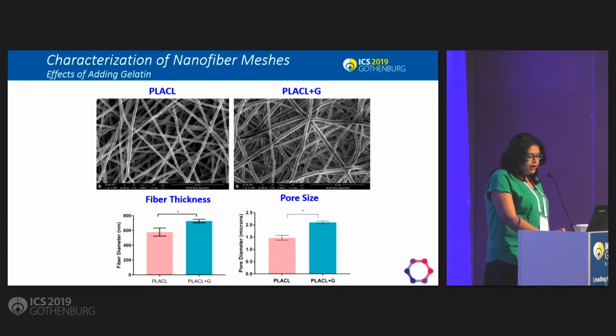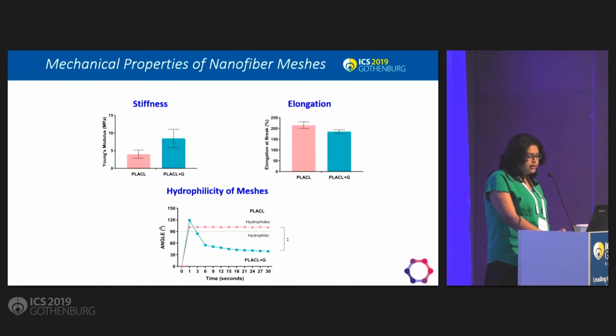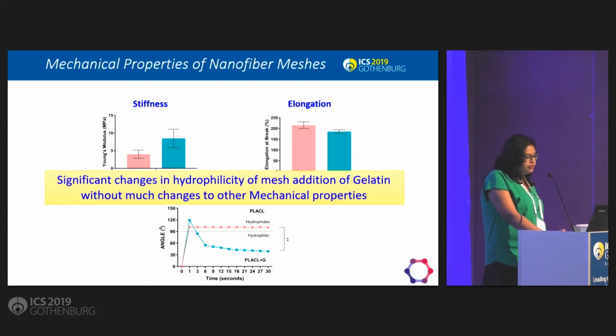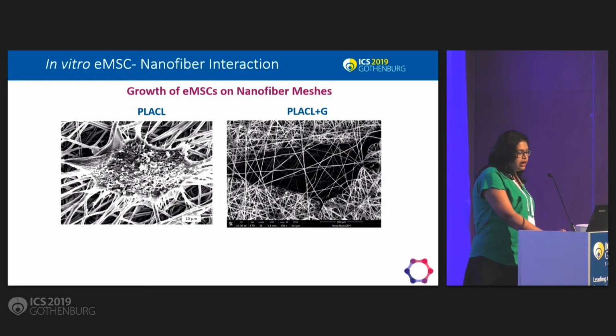So we fabricated two meshes. Mesh 1 was without gelatin. Mesh 2 was with gelatin. And we saw there's a significant difference in fiber thickness and pore size. We did not find much difference in the mechanical properties of these meshes, except that adding gelatin made it hydrophilic.